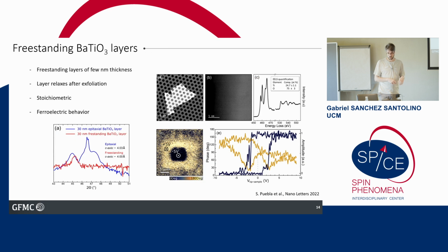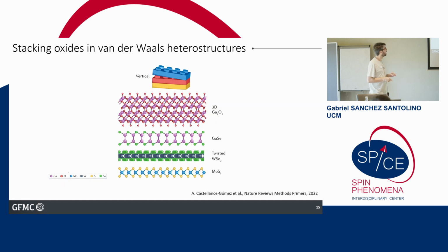We checked the properties of a single ferroelectric layer. It's still ferroelectric, which is the most important thing. The structure and the composition are still intact, and this is interesting: when we are delaminating the layer from the substrate, it's not constrained by the epitaxial match with the substrate, and it recovers the lattice parameter of the bulk. So we are getting bulk-like ferroelectric layers a few nanometers thick. And now we can just stack it with any other material, other three-dimensional materials, other 2D materials. We can do twisting, we can do whatever.